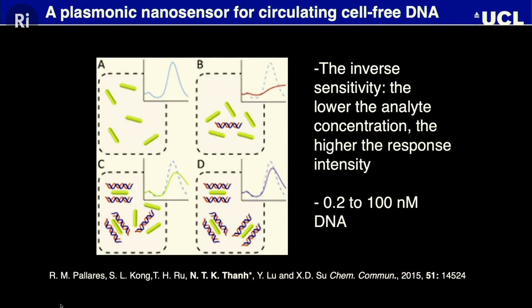It's a molecule that is positively charged, and then we're going to add DNA with the phosphate backbone. It's negatively charged. And remember the steric stabilization and electrostatic stabilization. So now you're going to neutralize the charge. So they are no longer repulsive, so they aggregate together. And because they aggregate together, you can see on the spectrum on the top right the change in the longer wavelength. So by seeing that change in the longer wavelength, you can do the detection.